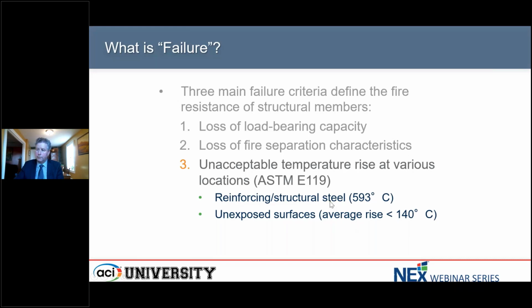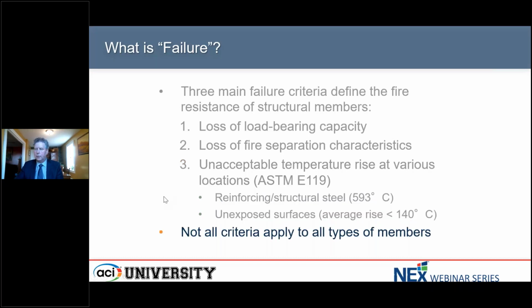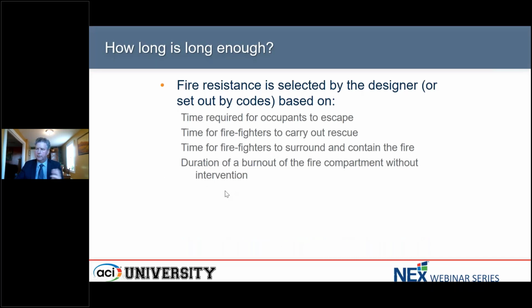And for reinforcing steel or structural steel in a reinforced concrete slab, for example, if the temperature in the reinforcing steel reaches about 600 degrees centigrade, which is about 1200 degrees Fahrenheit, or a little less than that, then at that temperature, reinforcing steel and also structural steel both have about half the strength that they had at room temperature. And so typically when we have fire, we know that the loads are going to be less than we expect in other loading circumstances. So we expect that if the member has about half of its original room temperature strength, it'll probably be okay for the loads required in fire.